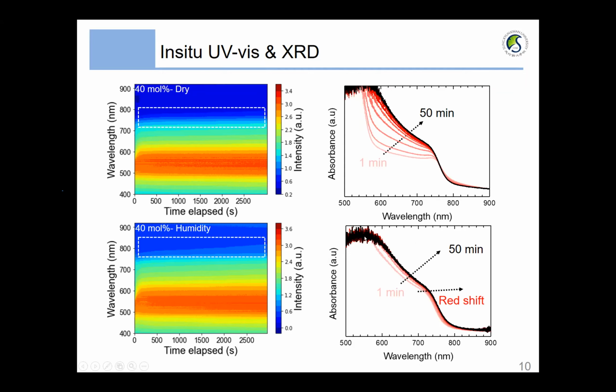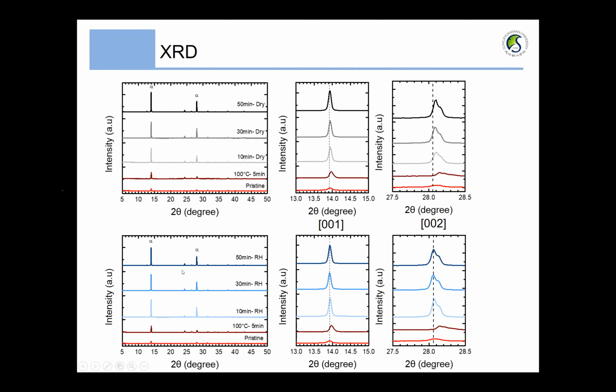We also observed a significant redshift in the onset value for the films annealed under humidity, while the dry condition shows no visible changes, which implies compositional changes from the humidity condition. So in order to investigate the compositional changes from the humidity condition, we continued to measure the XRD.